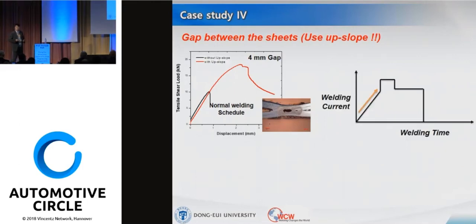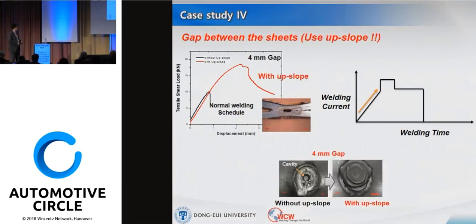And here's the tip. When you have a gap, please use the upslope. If you use the upslope, we were able to get about double the tensile shear strength. Then we checked the actual failure type: without upslope, there's a lot of cavity. With upslope, button failure and very small, very limited cavities.